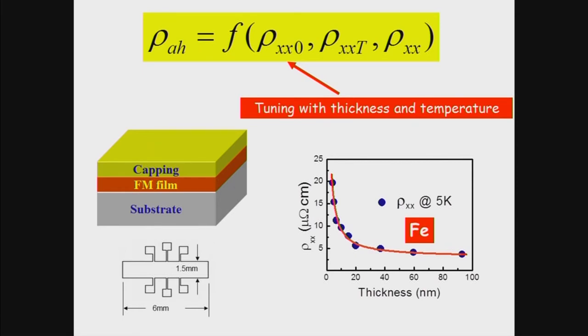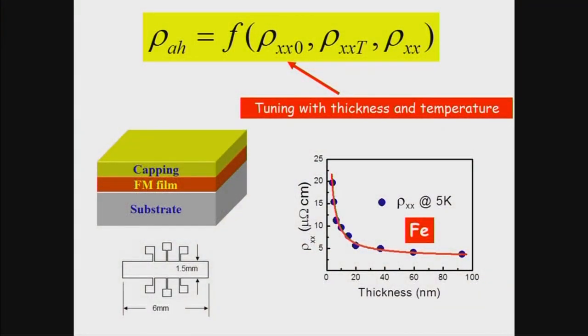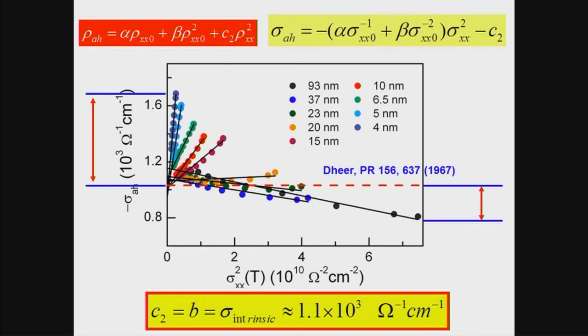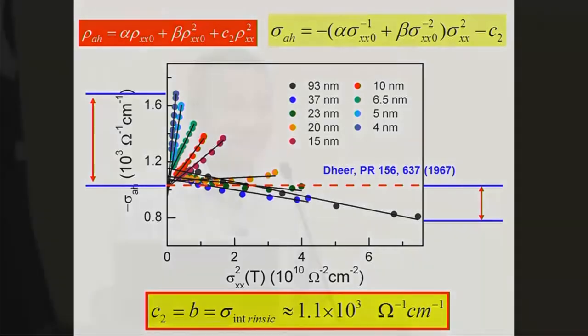I don't want to go into the detail, just tell you that we adopted an approach quite different from the traditional one. We are using the finite size effect of the residual resistivity as a function of film thickness. And this way, phenomenologically, we establish the scaling with three terms. This is the skew scattering, it's only related to rho_xx0, not the total resistivity. And this is the side jump, rho_xx0 squared. And this is a Berry curvature term.